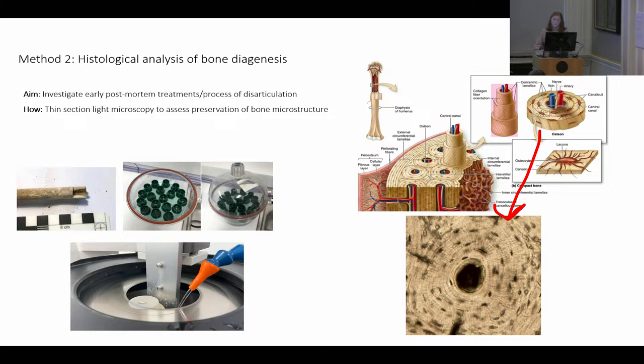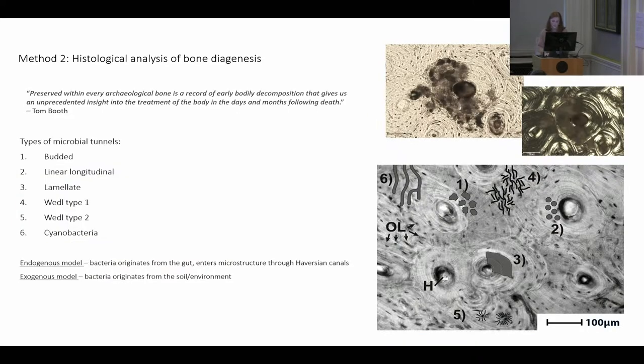And the reason we tend to use long bone is because the microstructure is dense and consistent along the whole bone shaft. So we take a transverse section, like what's shown here, and we're looking at the osteons, which are the main building blocks of long bone. They're these little circular things here. They have a central hole in them called the haversian canal, and these are used to transport nutrients through our bones during life. And the structure around the haversian canals is made of little layers of collagen, and this is called the lamellar structure. And the little holes that you see oriented around the larger haversian canal are called osteocyte lacunae, which is where the bone cells live. And the little striations between them are called canaliculi. And like haversian canals, these transport nutrients through the microstructure, and they're like little microscopic highways within the bone.